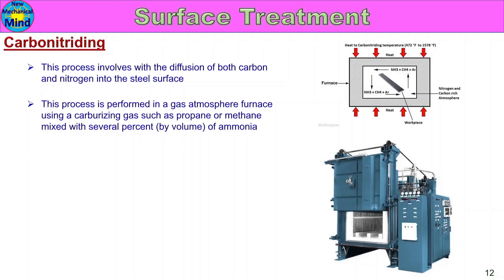This process is performed in a gas atmosphere furnace using a carburizing gas, such as propane or methane, mixed with several percent by volume of ammonia.